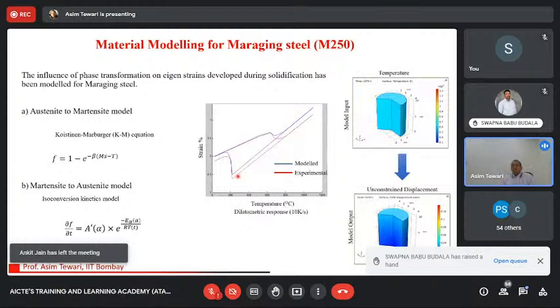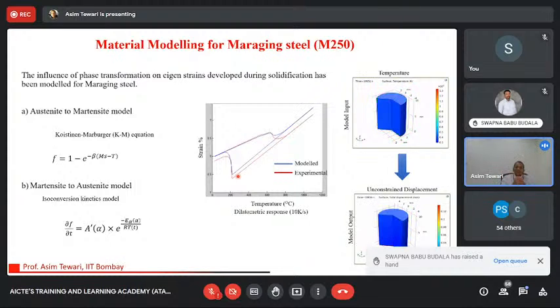So what I'm trying to tell you is that now you have a heat transfer process. The heat transfer process leads to thermal expansions, but you also have solid phase transformations going from martensite to austenite and austenite to martensite. And all of these put together will lead you to your eigenstrains. And this has a hysteresis, which means if I just tell you this temperature, you can't tell me what strain it would be, because it will depend upon history. If I started with martensite and I heated it up and I'm at this temperature, then I will have this strain. But if I started with austenite and I'm cooling down, then at the same temperature, I'll have a lower strain, which means that you need to know the history also, not just the current state, to know the entire eigenstrain. And all of this eigenstrain, depending upon the boundary condition, will lead to residual stresses. So that's the bigger picture which you need to understand.